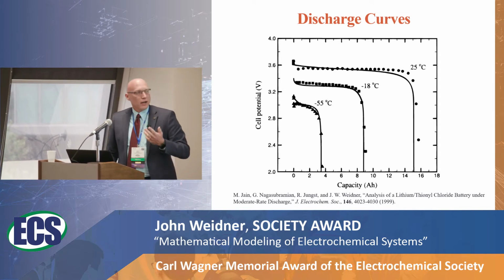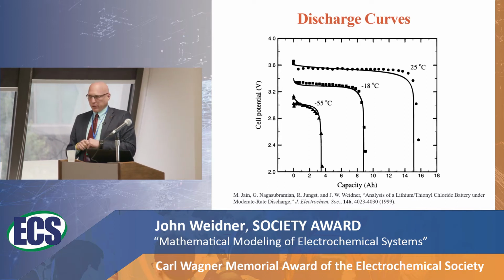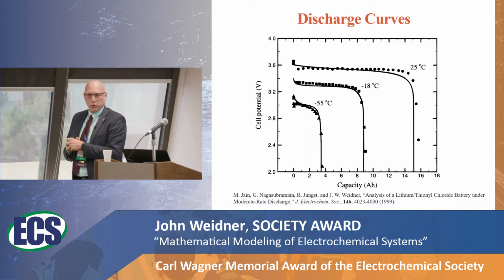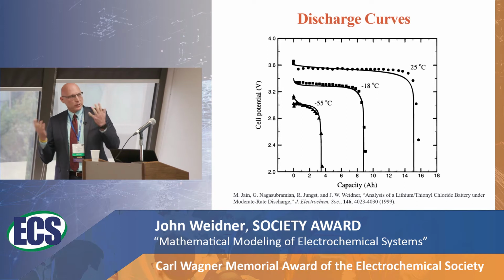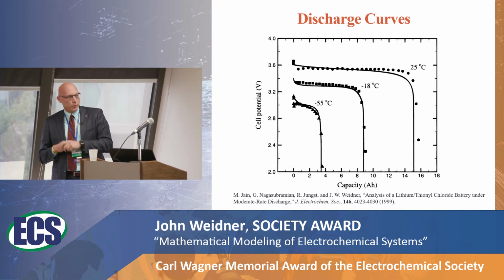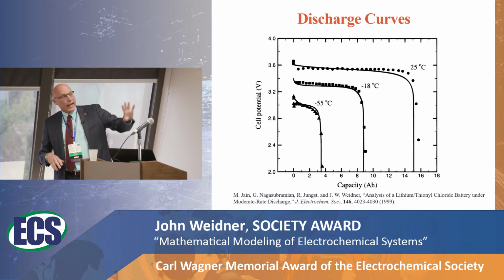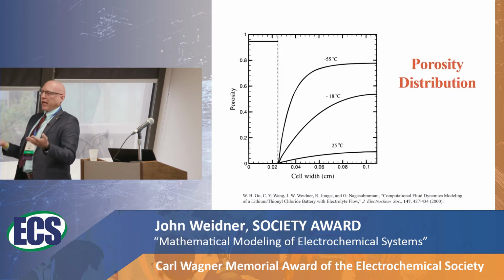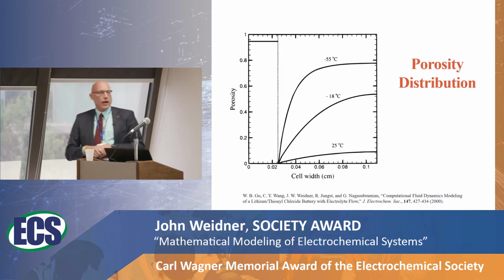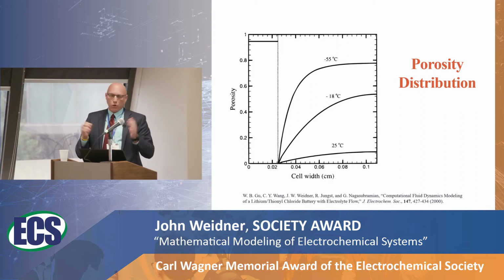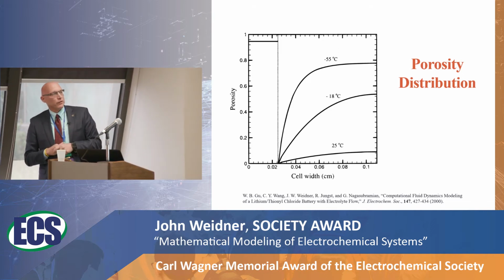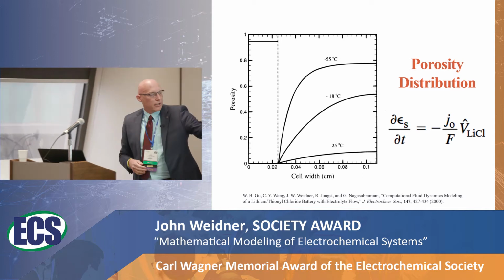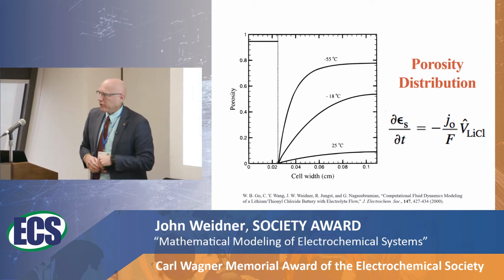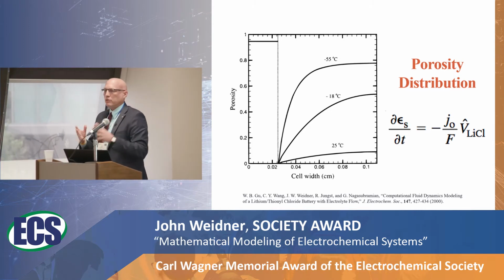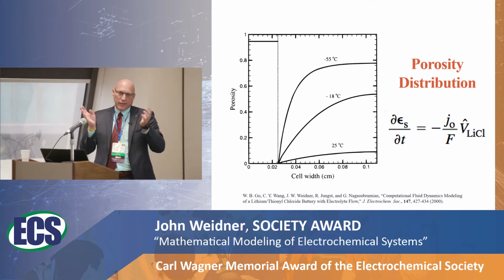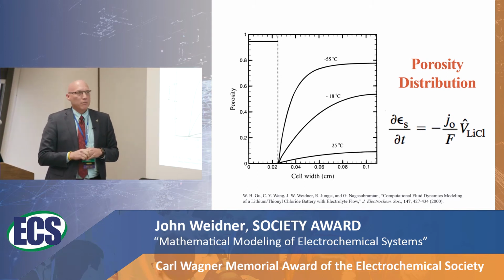So with that understanding, one of the things that we can look at, again, related to the reaction distribution, is what does the porosity distribution look like in the porous electrode? This is the porosity distribution at the end of discharge, when the battery voltage dropped off the cliff and you can no longer use it, and I show it for 3 different temperatures. What we see is that at the front end, the battery died because the porosity went to 0. We've completely filled the pores in the front. You can't get ions into the back of the electrode.